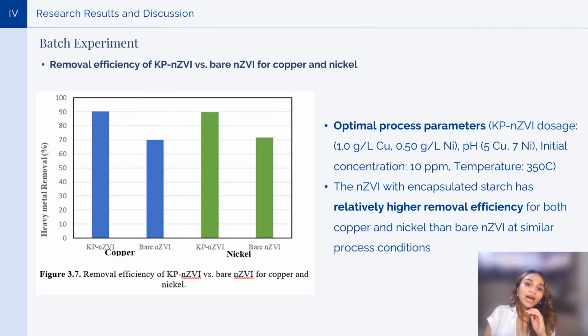and nickel. At optimal process parameters gained from the previous experiment, the nZVI with encapsulated starch has relatively higher removal efficiency for both copper and nickel than bare nZVI at similar process conditions. This implies that the starch encapsulated in the nZVI can improve the steric stabilization of nZVI, hence improving its removal efficiency of heavy metal in synthetic wastewater.